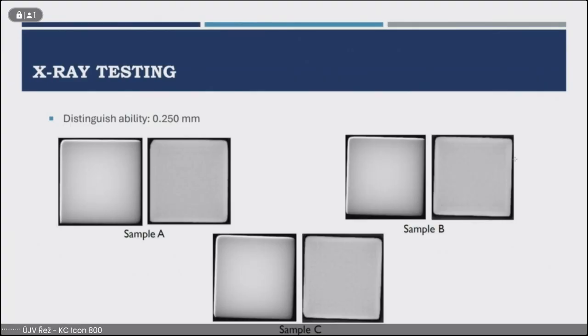As you can see on these pictures, this method did not observe any presence of any pores. Also, in that case, the samples have defects, but these defects are under the distinguishability of this method, so it should not observe any presence of the pores.